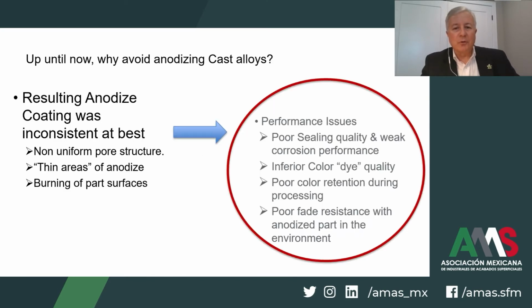Performance issues that have traditionally resulted from these three problems include poor sealing quality, equated to low corrosion performance, inferior dye quality, and poor color retention, both during and after the processing, and in use out in the application, where the color would fade, which was poor resistance to the environment. These were all problems that needed to be overcome by looking at an improved process.